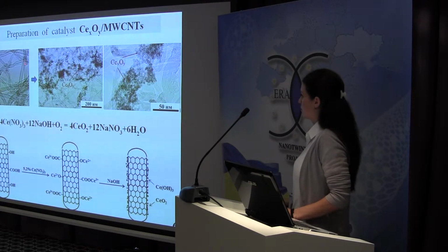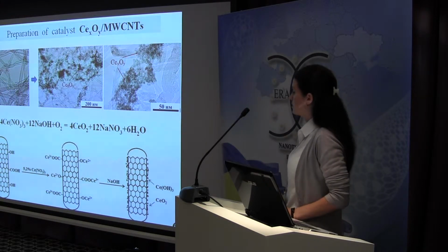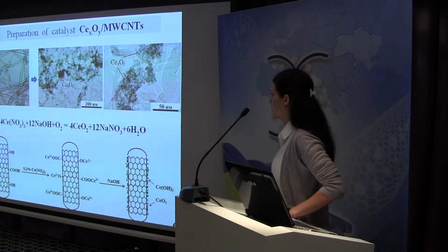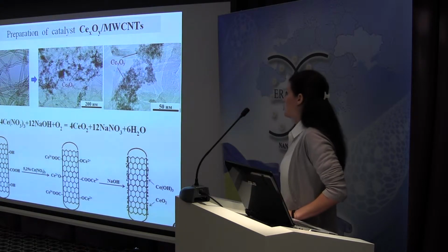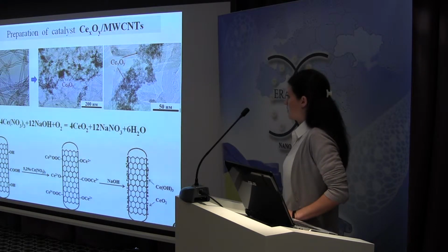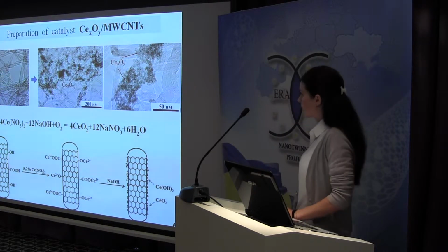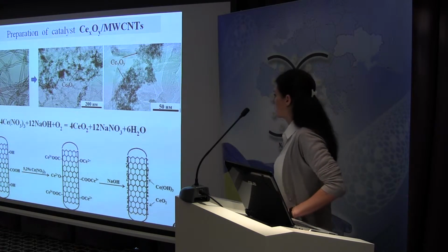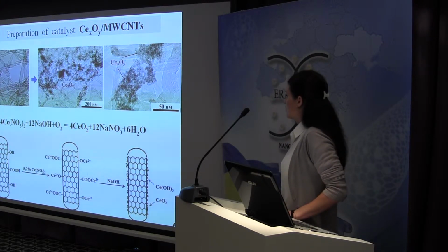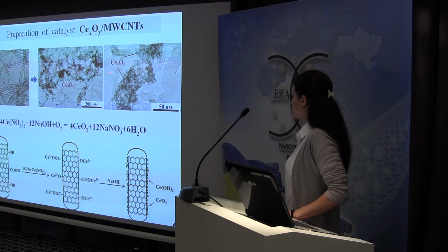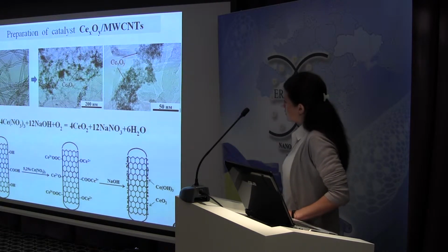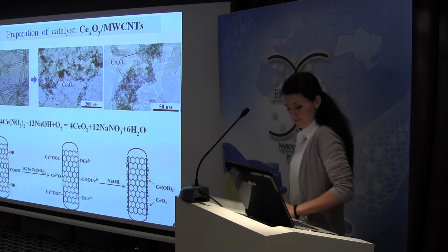We used multi-wall carbon nanotubes, which were synthesized by the CVD method, employing an iron-containing catalyst. The carbon nanotubes have an external diameter of 10 to 40 nanometers, specific surface area of 200 to 500 square meters per gram, and purity of about 99%. Analysis of spectral characteristics showed the formation of modifier particles on the surface of carbon nanotubes. Their size is 6 to 10 nanometers.